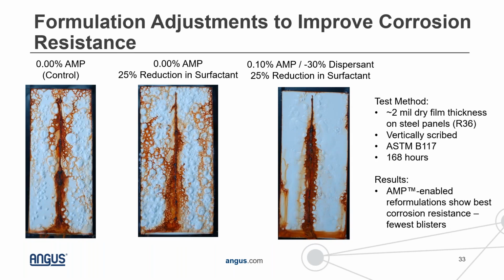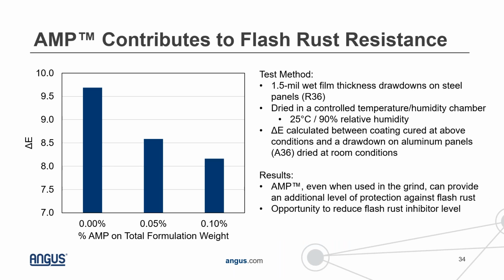We also see that play out in the traditional ASTM B117 salt spray testing. So in the results, you see a lot of blistering in our control formulation. The same is true for the sample where we reduce the surfactant. But if you compare this to our reformulated sample, there's a significant improvement in the corrosion resistance that we're seeing with these formulation changes. Another potential benefit of AMP in this formulation is that we believe that AMP can contribute to the flash rust resistance of the coating.